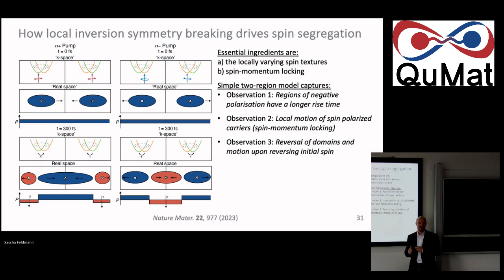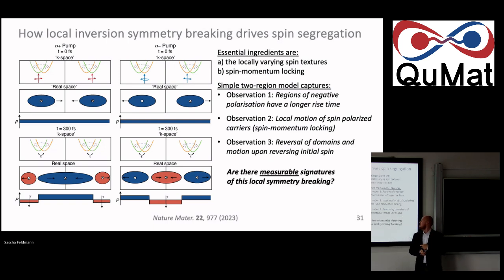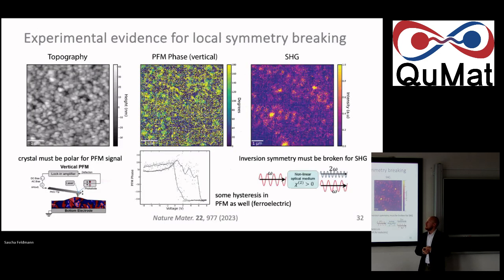So spin scattering after some time, and this inversion symmetry breaking that I've kind of just a priori now predicted to be there, apparently. So the last thing is, can we find measurable signatures of such local inversion symmetry breaking to give rise to this spin momentum locking? And we think we have identified a few cues for this at least. So here you can see, for example, the piezo force microscopy vertical phase, which is varied quite a bit and actually shows some hysteresis. Not an expert in this. This was done by collaborators, therefore with a pinch of salt.